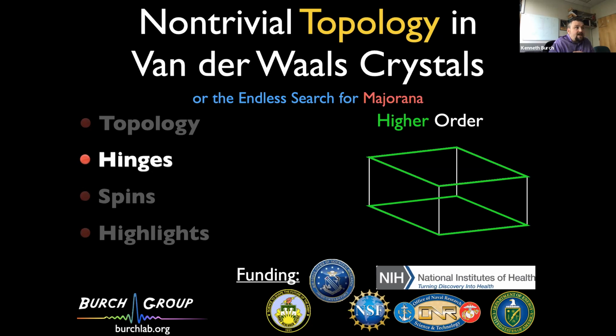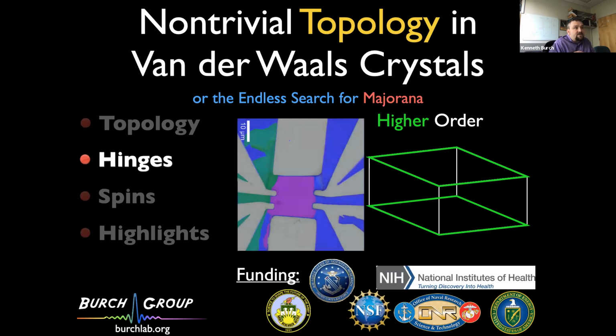So to try to prove that, my group looked at this iron telluride selenide, and this is a picture of one of the devices we made that I'll show you, where the purple is FTS, which is meant to be one of these higher order topological superconductors. And then the sort of yellowish bits are the contacts. And then the greenish part is actually an insulator, hBN. And the purpose of this hBN was to cover up the hinges on one side such that we can make identical contacts to the two surfaces, where one of them touches the hinge, that's the one on your right, and the other sets touch just the bulk.